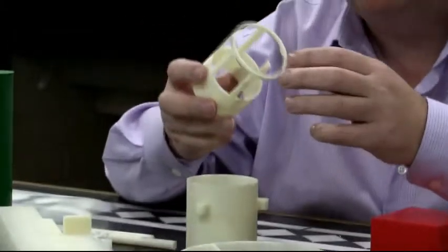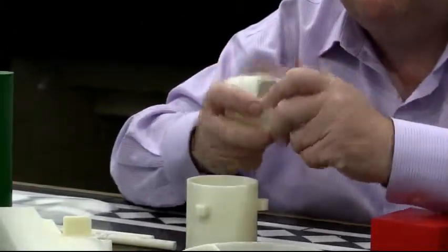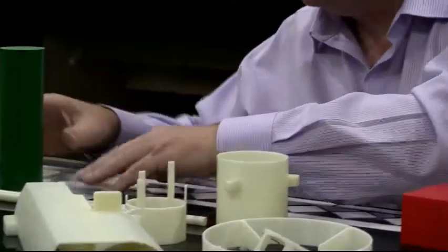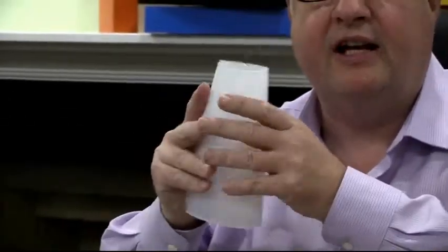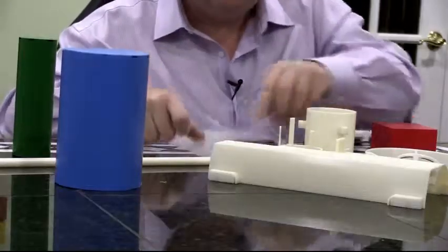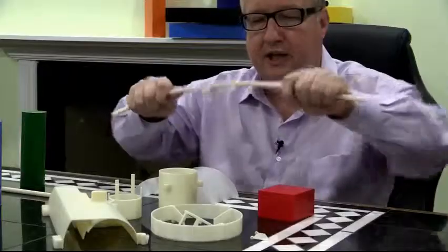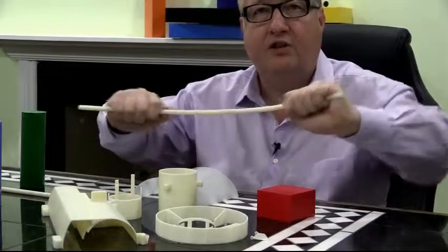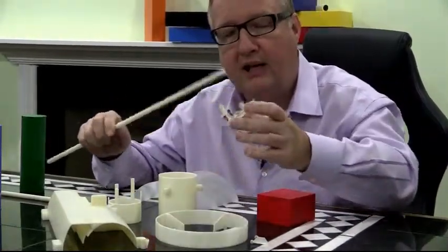This is an example of a prototype. And you can see that because of the way the layers are built, the screen is very fragile. Whereas our injection molded parts, even when they're very thin, are very flexible. And our rods that are injection molded out of the exact same material are very, very strong and flexible, as opposed to being brittle and breaking along the bond lines.